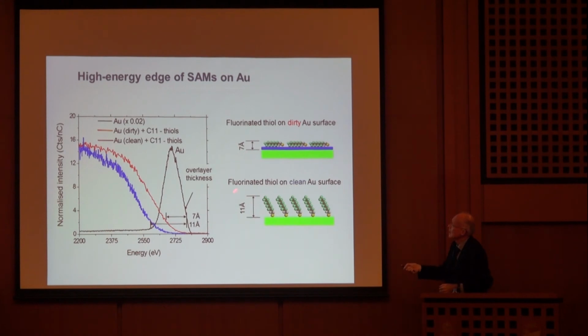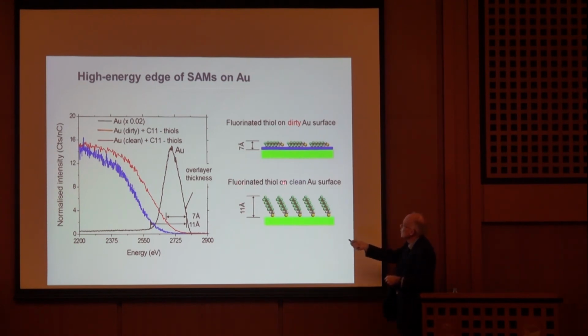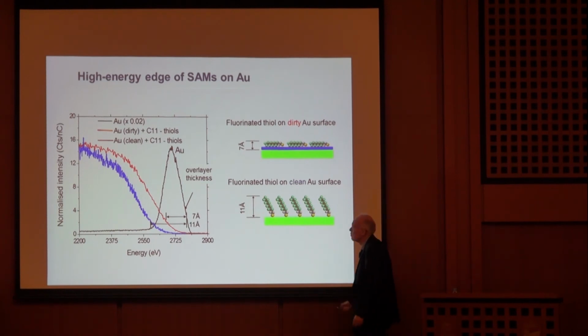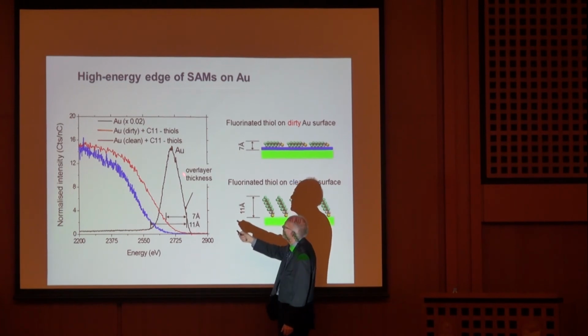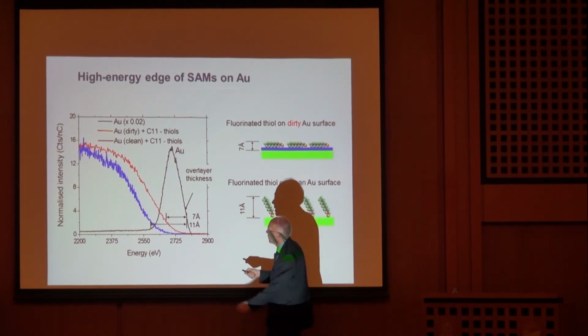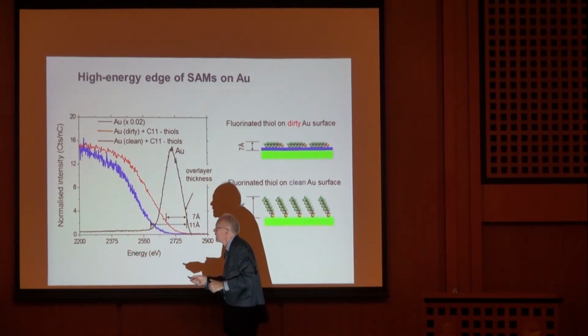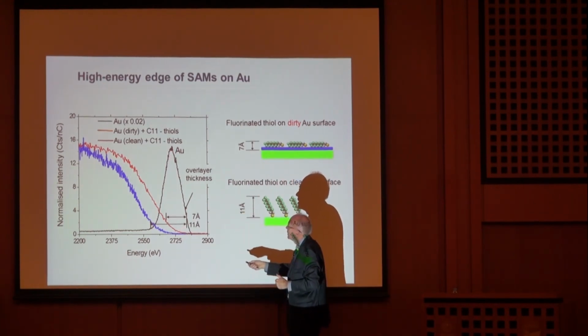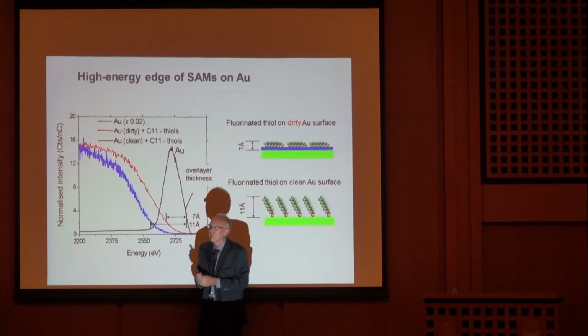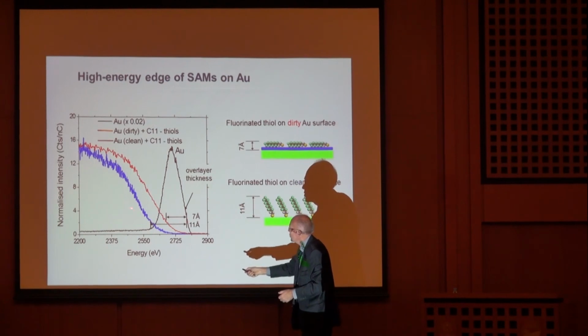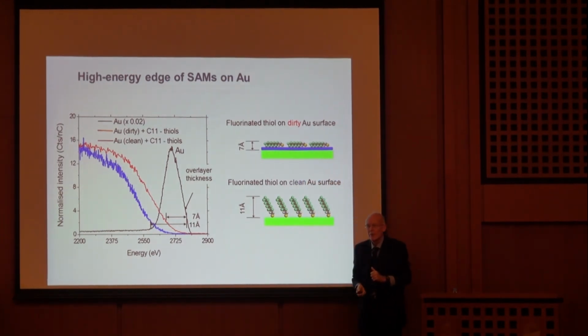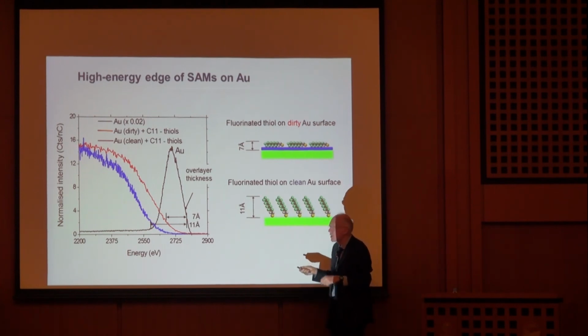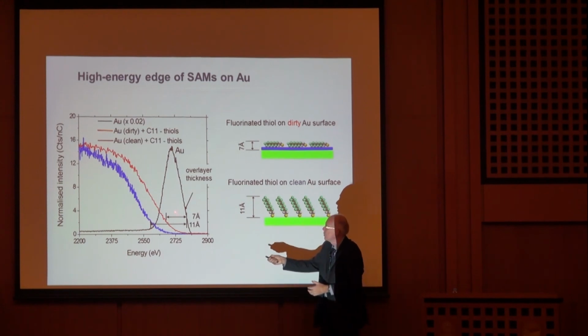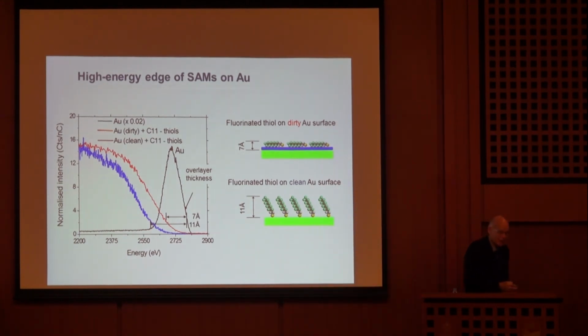Where you do, for instance, self-assembled monolayers, you can see whether they are standing up, what the thickness is. In this case, it's fluorinated thiol on gold, which is a very simple one. If it was just gold on top, you would get this peak with a little bit of background for gold in deeper layers. When we put the thiol on top, this peak disappears. And if I amplify this by a factor of 50, I see there's an onset. That shift tells me whether the layer is 11 angstrom thick, or in the other case, it's only 7 angstrom thick. That shift is very characteristic for the energy loss going through that layer in and out. And so you can determine with the accuracy of about 1 carbon atom how thick that layer is.